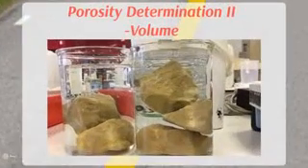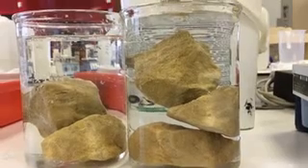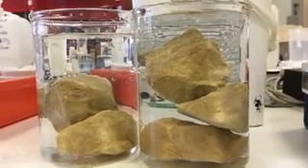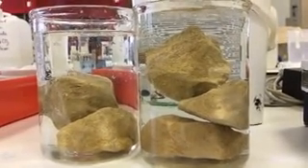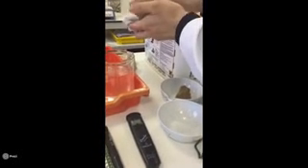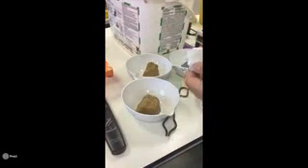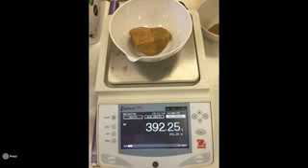The sample was then impregnated in distilled water until there were no air bubbles escaping from the rocks. By gently removing the excess water on the rock surface, the wet weight of each clast was obtained using the same subtracting method. The volume of pore space can be calculated through the mass increase, which was only due to the inner pore space being fully occupied by water. The bulk volume of each clast was measured via the volume of displacement.